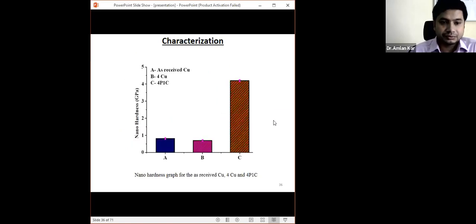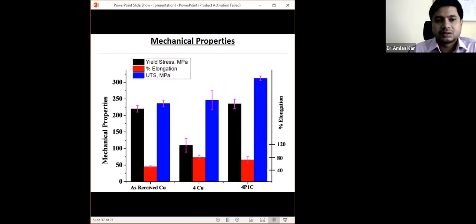So what are the, and compared to the copper there is also an improvement in the nano hardness of the particles. What are the reasons for that? Because we are getting the advantage of matrix refinement as well as particle refinement. The particles are in the nanometer range, and because it is the nanometer range, as we already discussed, the surface to volume ratio is very, very high, and the aspect ratio of these particles is also very, very high. So therefore we can get activity at the interface level also, and therefore the bond between the particle and the matrix is very, very strong, and therefore we get very good mechanical properties in terms of yield strength, elongation, and the UTS.